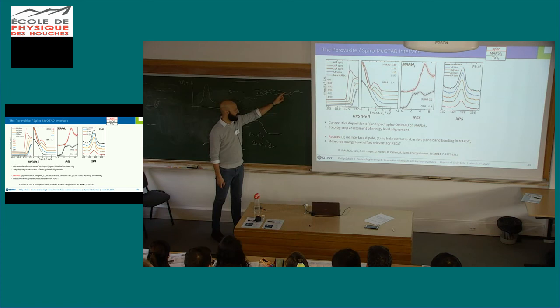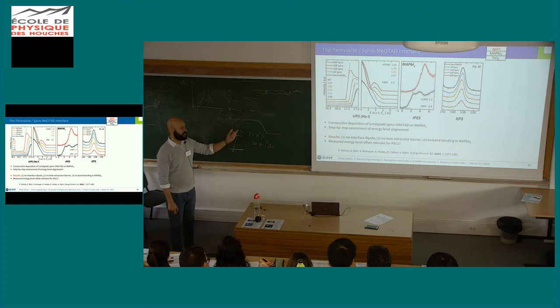It's, in this sense, a qualitative study. We've done this also for ALD films that cover the perovskite very conformally, and then after 4 nanometers, you see nothing of the perovskite anymore.